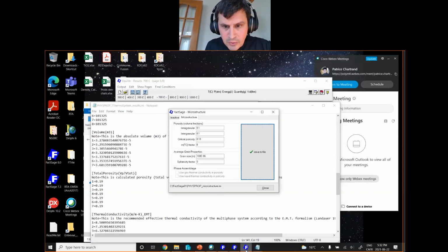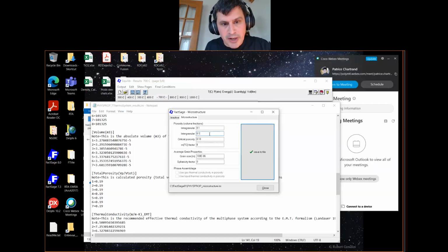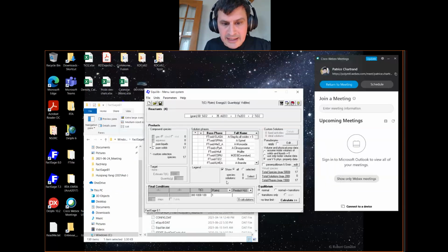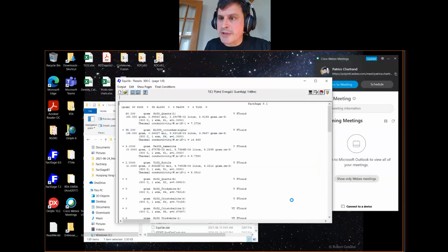If now I go to the microstructure program and I put an intergranular porosity of 40% and I save, and I will go back to equilib and redo the calculation, I will get the same values for the thermal conductivity of all the phases at the same temperatures, with the same phase fraction.